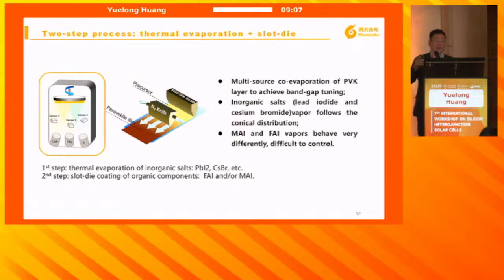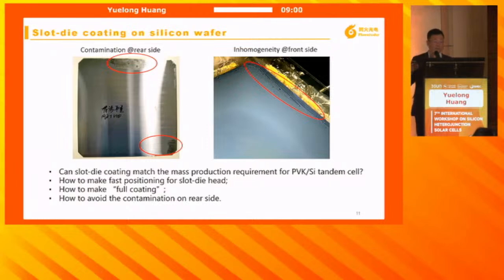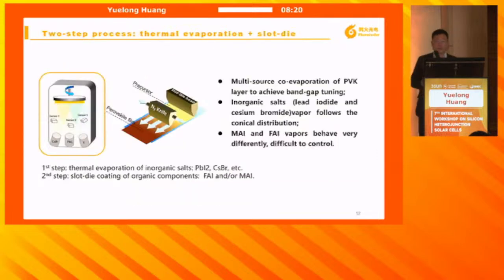But therefore, we think maybe for mass production, using slot die is not the best solution. Not only because of the edge side, but also if you use slot die, you always need to position the head on the wafer, and sometimes the wafer may not be so flat. So you have to handle everything technically. It's quite difficult. Of course, we will have some solutions to make a better slot die, but we also show you some other technology with which we can make a similar or good quality film, with very good control of the film quality.